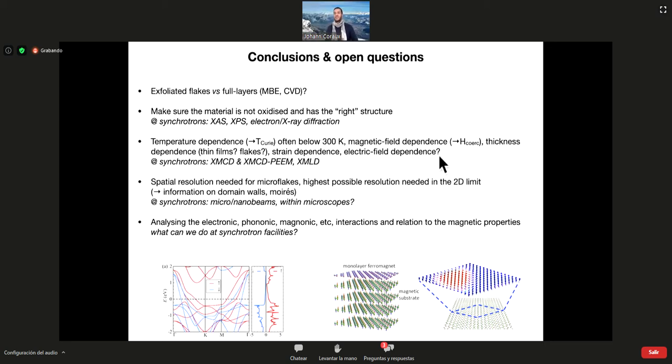Then there are practical details, which are maybe not so anecdotic, with the preparation of the samples. So we've heard about transferring samples grown by MBE with a suitcase, which is obviously a good way. You could think of capping strategies as well with materials that you can degas in UHV. And I know that there are some XMCD beam lines where they couple the UHV system with a glove box. So you can imagine preparing the material by exfoliation and directly entering it into the UHV system without seeing air, which could also bring a lot of flexibility.